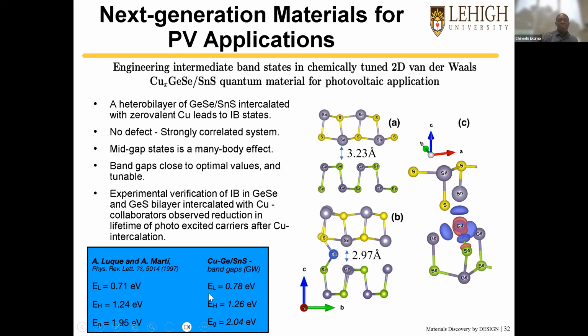So our particular material, as you can see here, their energy band, that is their sub-band gap, low level, high level, and their intrinsic band gap are in line with what Luque and Marti had initially proposed to be the optimized band gap regime for materials that could be used as intermediate band systems.